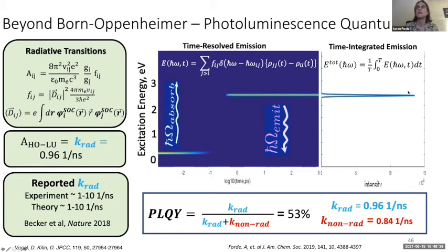So this figure just looks at intensity, but in experiments, another important quantity is how efficient the emission is, which we can compute from computed radiative and non-radiative rates, where the radiative rates come from these Aij Einstein coefficients shown in the top left, and the non-radiative rates come from the Redfield tensors. And we can see that from those rates, we get a fairly efficient PL quantum yield. So we get high intensity and fairly bright emission.